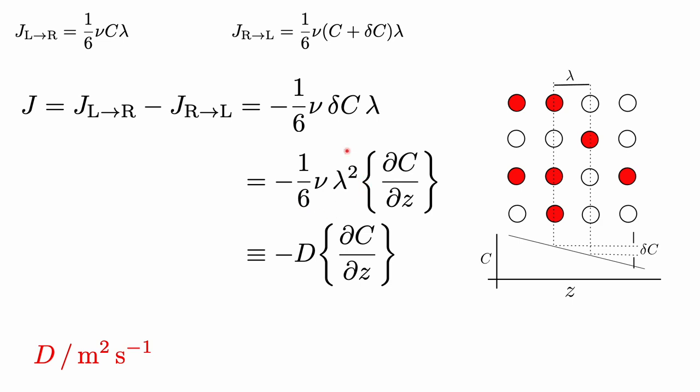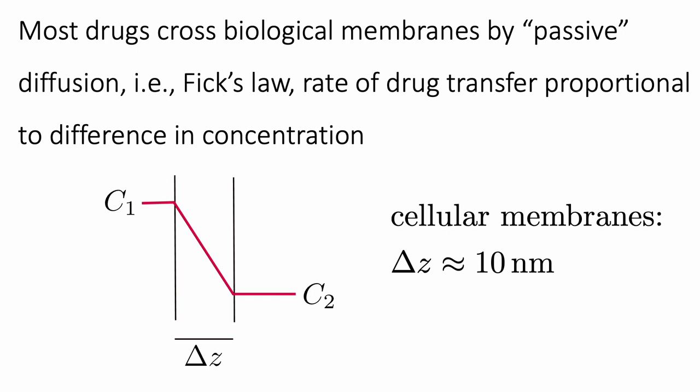And this then becomes what we call the diffusion coefficient, D. You know, it's a function of interatomic spacing and the jump frequency. So this is, of course, Fick's law. And because the units of flux are atoms per meter squared per second, and we are multiplying the diffusion coefficient by a concentration gradient, then the units of a diffusion coefficient will be meter squared per second. Just to give you an example of the application of the law that we have just derived, and that's known as Fick's first law, that the flux is proportional to minus D times the gradient of concentration.